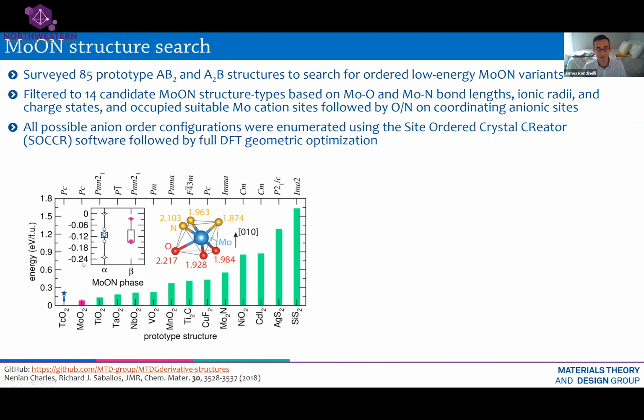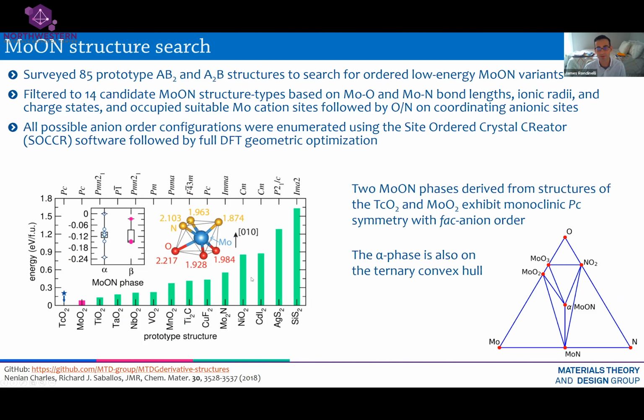And in addition, what he found is that the lowest energy configuration for the anions, remember this is a compound that not only has oxygen but nitrogen in it, is the one shown in this inset here, where the nitrogen prefer to share one face and the oxygen prefer to share one face. If your background is in chemistry, this is called a FAC configuration of the octahedra, compared to a cis or trans configuration. And the FAC conformation is the one that's most stable for this molybdenum oxynitride.